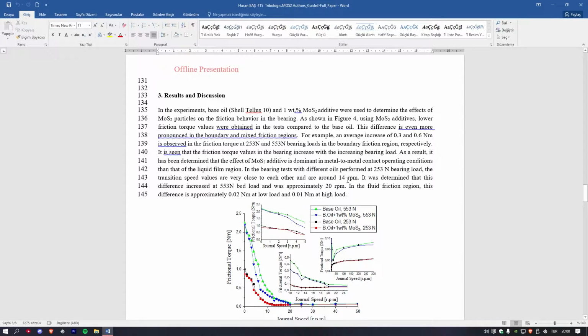In the bearing test with different oils performed at 253 Newton bearing load, the transition speed values are very close to each other and are around 14 RPM. It was determined that these differences increased at 553 Newton bearing load and were approximately 20 RPM. In the fluid friction region, this difference is approximately 0.02 Newton meter at low load and 0.01 Newton meter at high load.